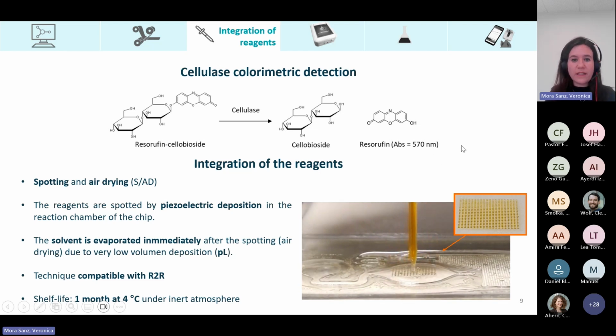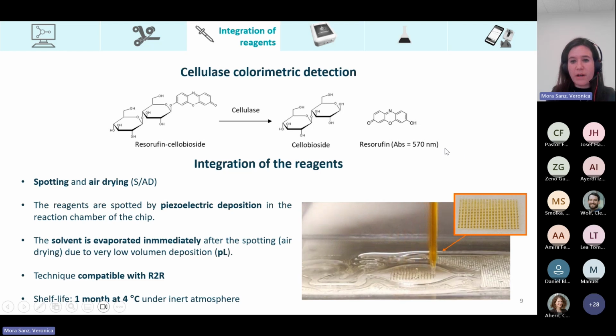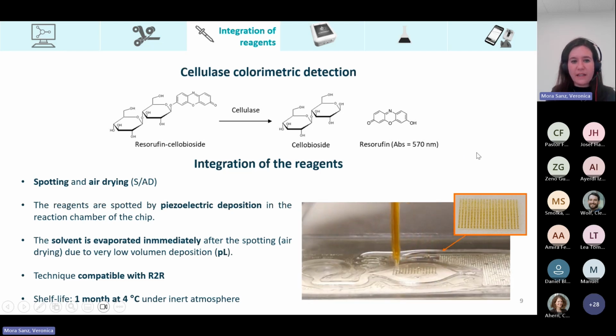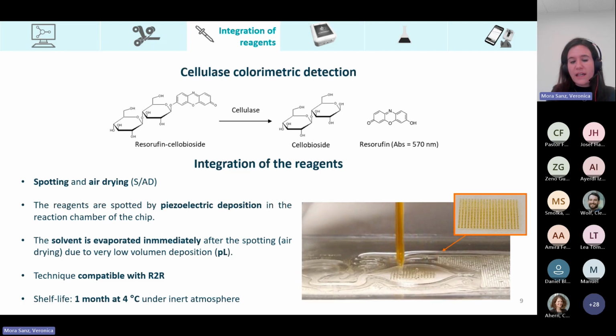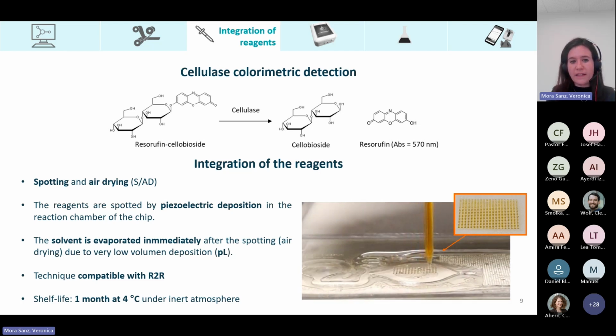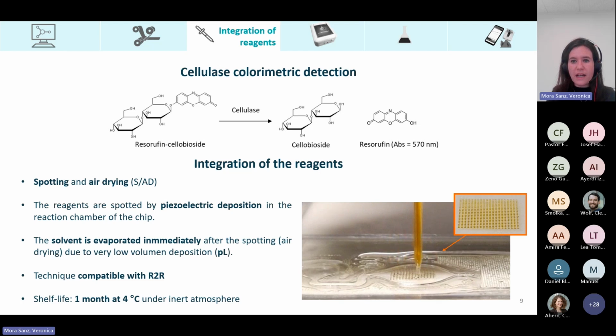In this case, the integration of the reagents was made by spotting by piezoelectric deposition directly in the reaction chamber of the chip, as we can see in the video. In this case, we are spotting a very low quantity of volume in the range of the picoliters. This is why the solvent is immediately evaporated. This technique is compatible with roll-to-roll manufacturing. And in this case, again, the shelf life of the chip is of 1 month at 4 degrees under inert atmosphere.